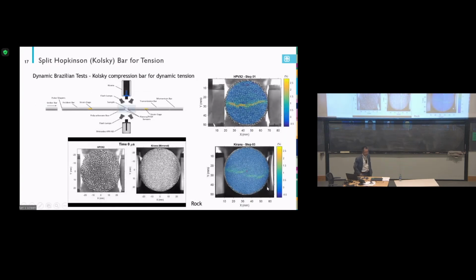And another measure. Because for a tensile test, you remember, you have to attach your sample firmly to the bar before the test. So usually we use a dog bone sample with thread. We thread it into the bar end so they can grab the sample and pull it. In a compression test, we just frequently use friction to hold the sample as we compress it. But for tensile, you have to use a thread or something like this.